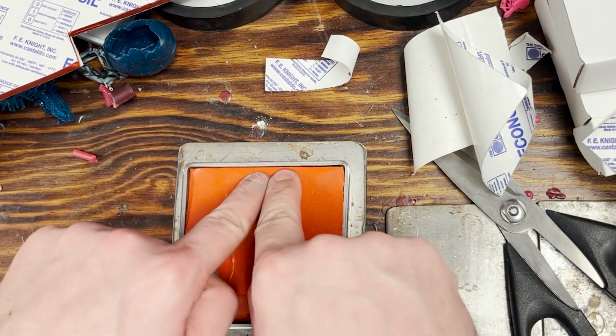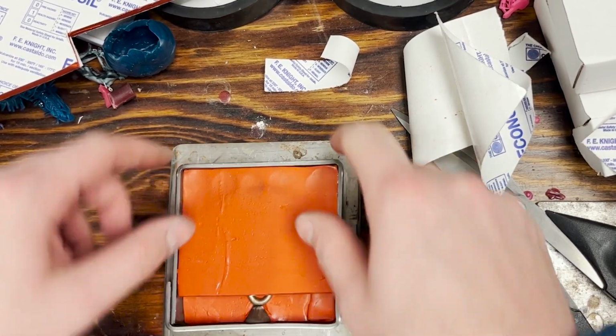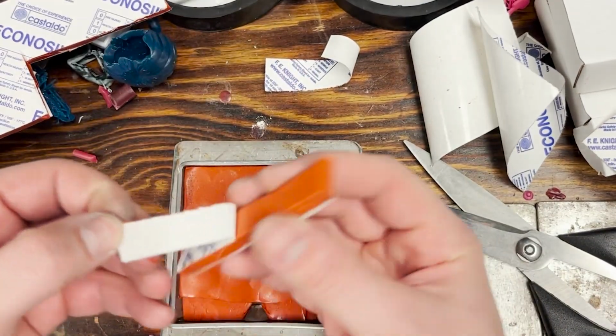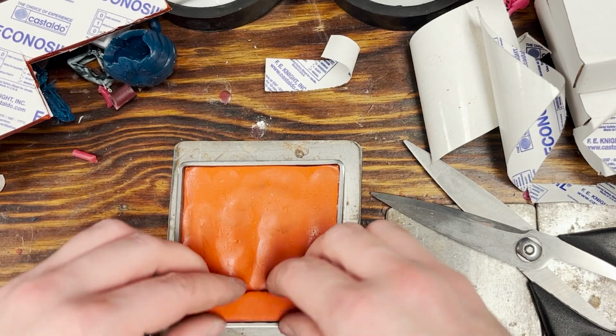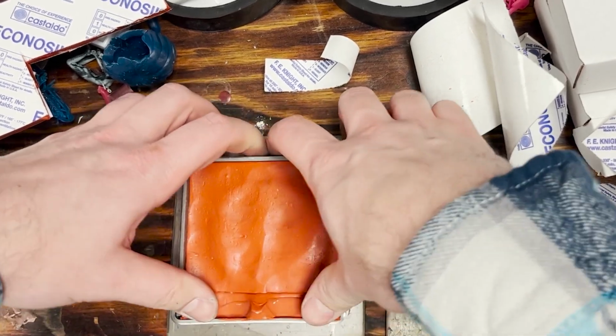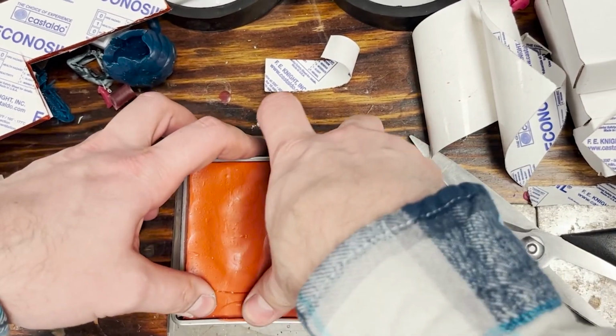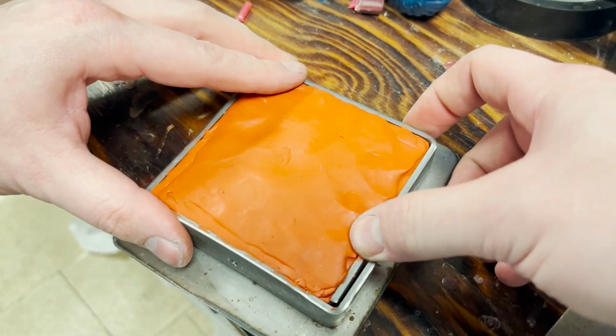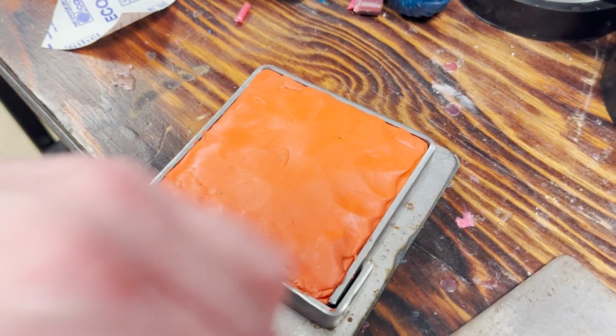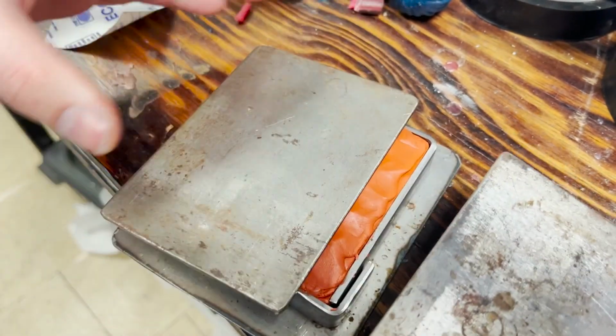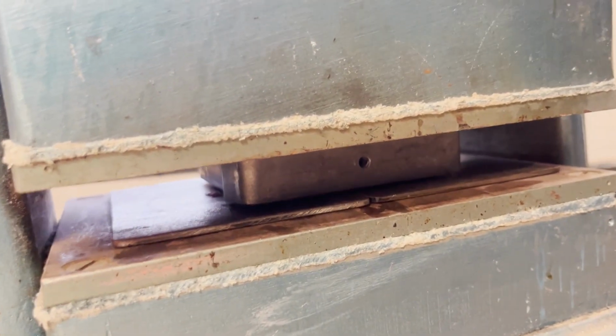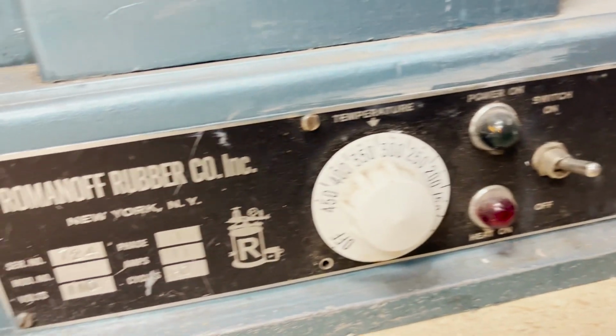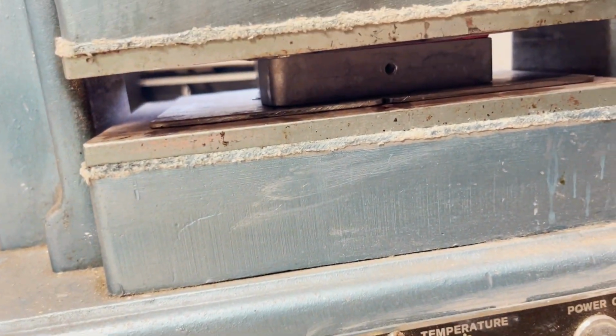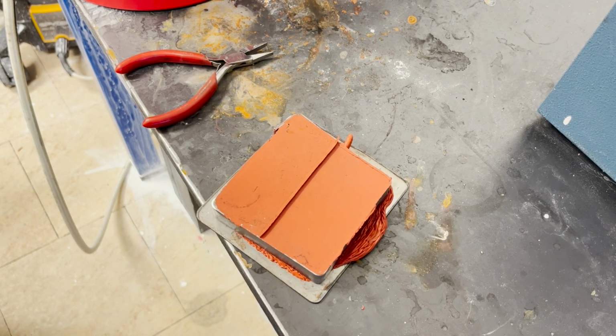According to the Castaldo website about this Econosil material, it is durable enough that it can be used to cut incredibly complex aspects of the mold, such as spirals, cores, flaps, and whatever else complex things you can come up with, so that you can ensure that you get a good injection. So I used the recommended vulcanizer settings for this material. I put it in with steel plates at, I think it was, 320 Fahrenheit, but it has a range between 320 and 350. The recommended vulcanizing time is 15 minutes per 6 millimeters of thickness in the mold. So that would equal out to about 45 minutes.